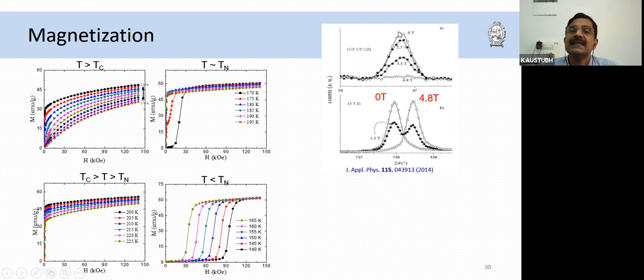You can see that this is the magnetic half-half peak, which disappears when you apply a 4.8 Tesla field. So that means the antiferromagnetic state is converted to the ferromagnetic state, and at the same time you can see that the nuclear peak, the 332 nuclear peak, shifts to a higher angle in field, telling you that the high volume cubic state has converted to the low volume cubic state. At any intermediate magnetic field, you can see that both the low volume and high volume states are present in this case. So this was very interesting as it is before when we started this.